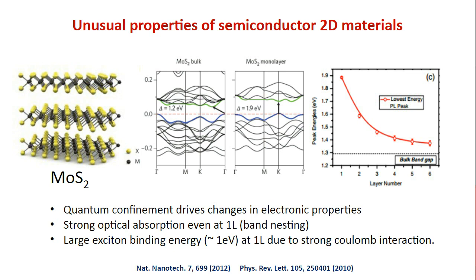We know that the absorption property increases with thickness. So even if you normalize that factor out, so per layer, the single layer has more strength than the bulk MoS2. So now this is huge, because now you can think about applying MoS2 for some nano device applications, right? And there are also other interesting things going on with MoS2, and I'll talk about the excitonic feature of these systems in a few slides. All in all, I hope that I've pointed out a few things that are very, very interesting about this material.